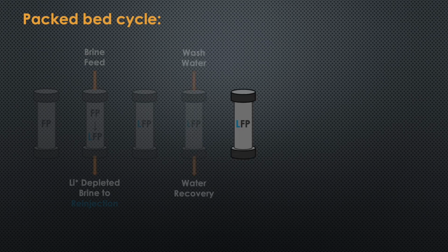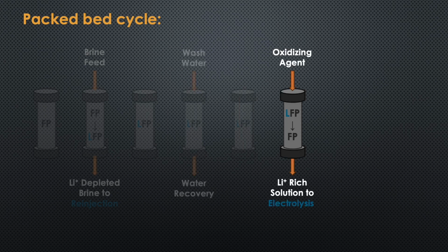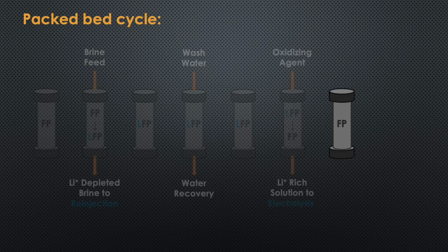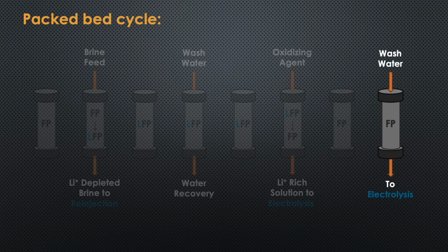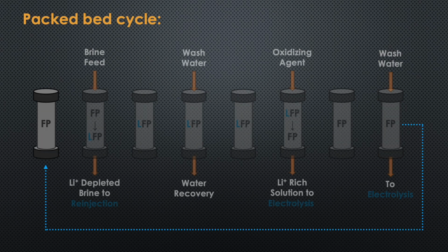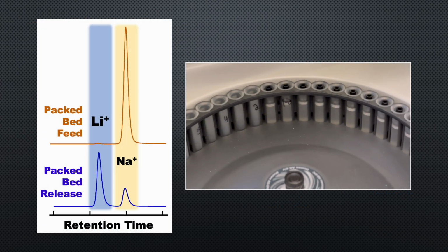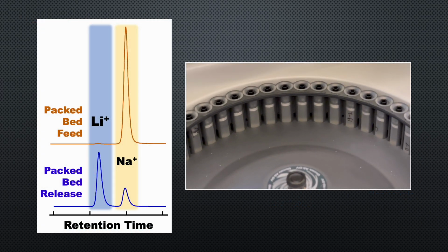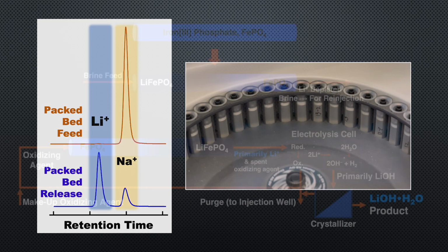At this point, lithium can be removed from the LFP bed using an oxidizing agent, which converts the LFP particles back to iron phosphate, or FP particles, and this results in a lithium-rich solution which is passed to our electrolysis cell. The resulting FP particles are further washed with water to recover any residual lithium, and that solution is passed to the electrolysis cell as well. This leaves the packed bed in the iron phosphate form, ready for another cycle of lithium capture from geothermal brine. Ion chromatography is used to evaluate the selective capture and release of lithium from solutions containing high amounts of sodium.